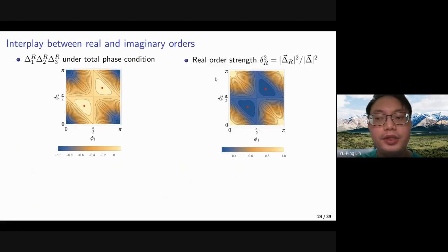So we should also characterize the strength of the real order in the phase diagram. We can see that at the corners, the strength of the real order has the maximum value 1, which corresponds to the purely real orders. And if we go to the bulk of the phase diagram, the imaginary orders start to emerge. In this case, the strength of the real order will decrease.